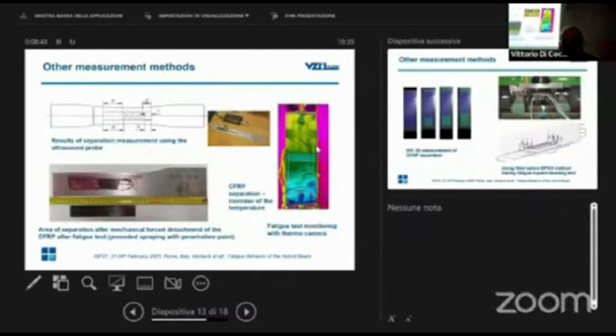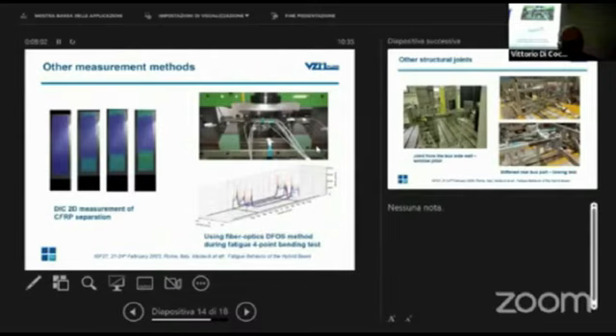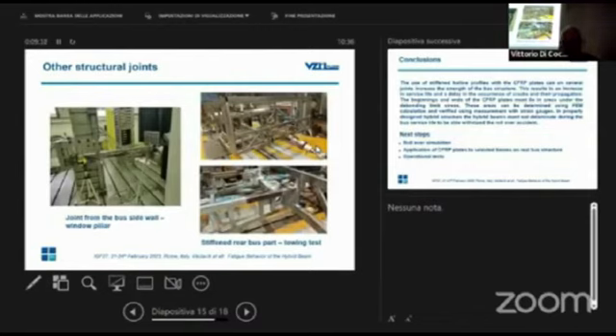Here are only some examples for monitoring, also with using other techniques for monitoring. So we use ultrasound, we measure with thermocamera. We have also digital image correlation, and also we use distributed fiber optic sensors for measurement of the strains on whole lines through the sample, which were integrated in the adhesive. This is an example of another structure part, which was side wall from the bus, and on the right side there is the monitoring of the distortions during the testing during 2 million cycles.